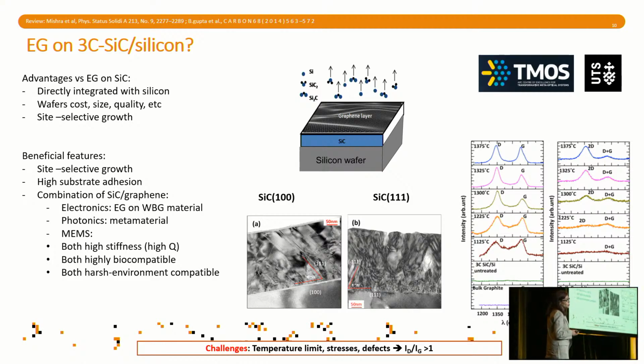Challenge number two is the temperature. The sublimation or thermal decomposition of silicon carbide works best at around 1500 and above. Of course, if we're working with silicon wafers, we have to be safely below 1400, 1414. So this is not something that we can reasonably reach without creating other problems. So that's another challenge, and there's more than that. This interface is extremely challenging. We not only have to think about how to solve the challenge of growing the graphene, but also what to do with this interface here. Just hold that thought, because I will get back to it towards the end of this presentation.